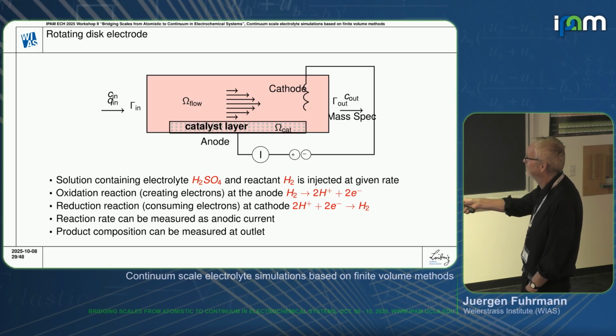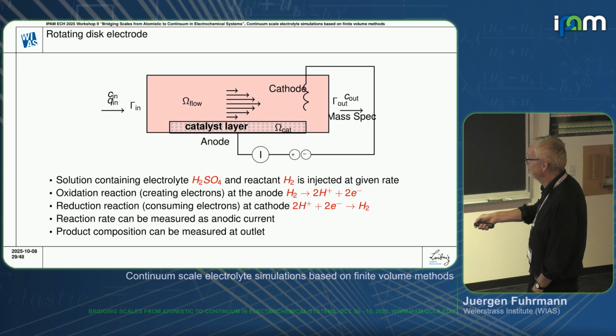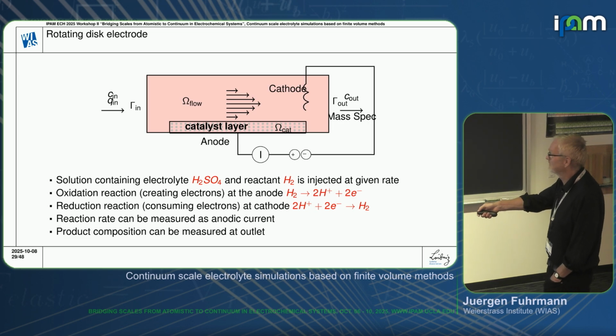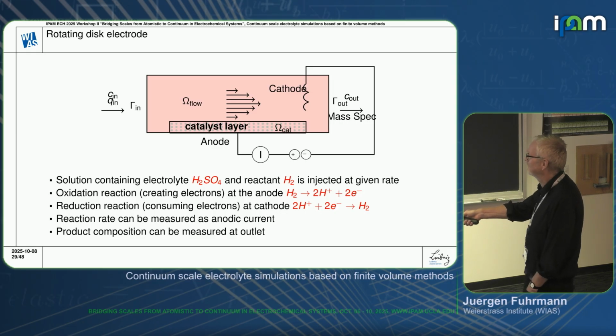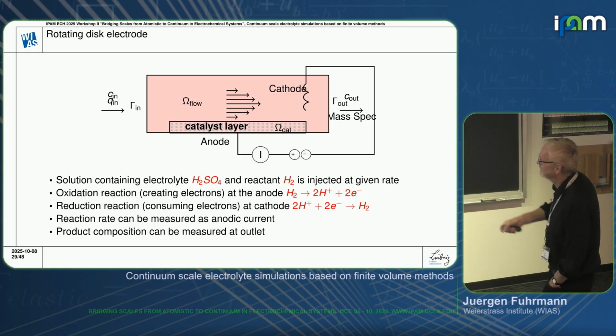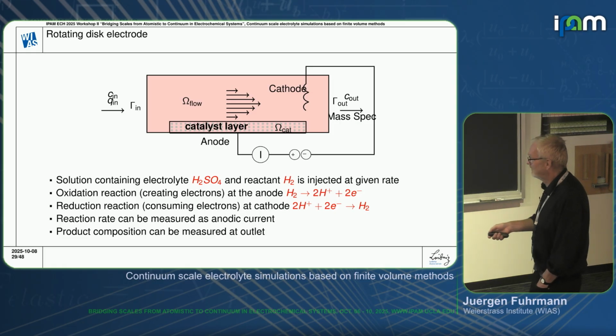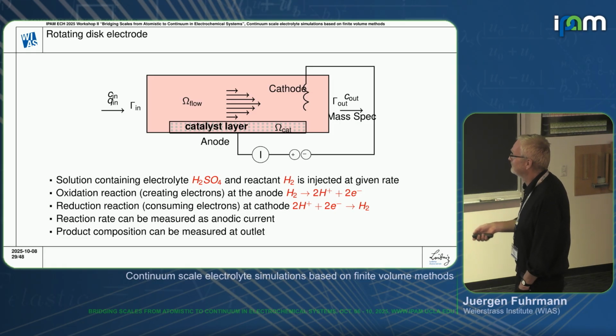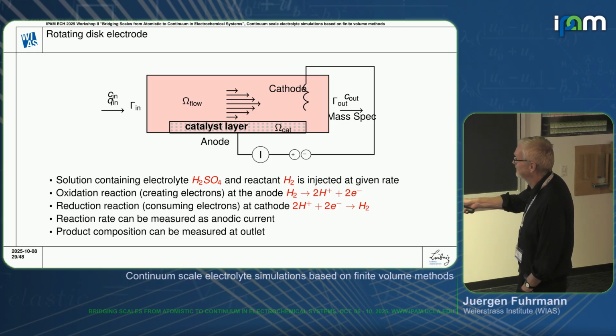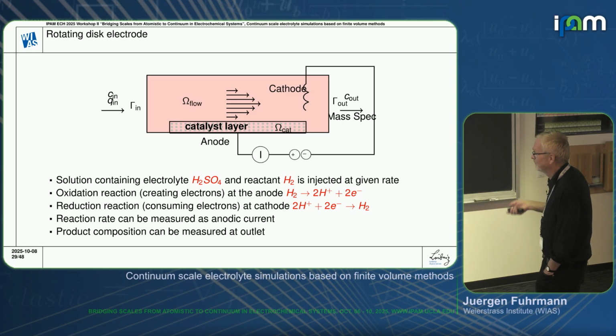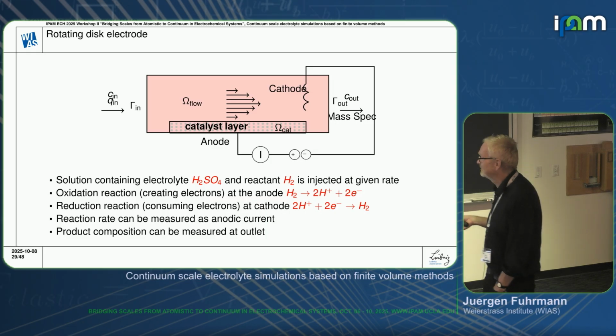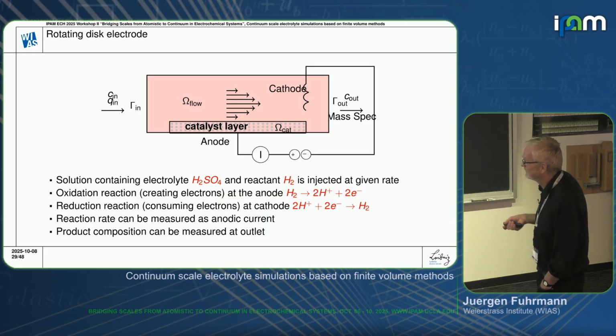We have some catalyst layer. We basically assume that we have some reactive species. In a particular case, it could be, for instance, just hydrogen, which is injected at a given rate. It reacts at the catalyst site. And we can measure the reaction rate as the anode current, and we can also measure the product composition at the outlet. So this is some kind of flow cell setup, which exists in different versions in different labs of electrochemists.